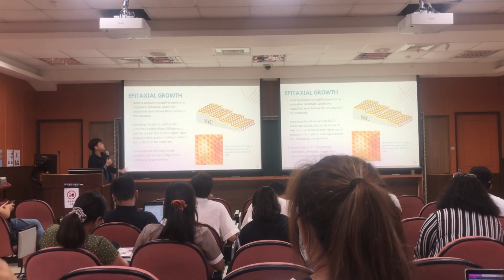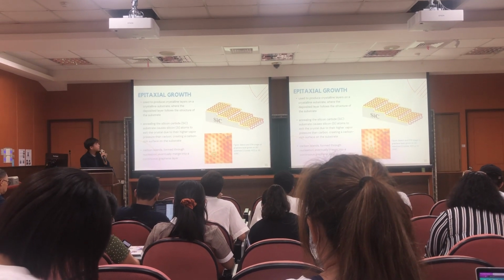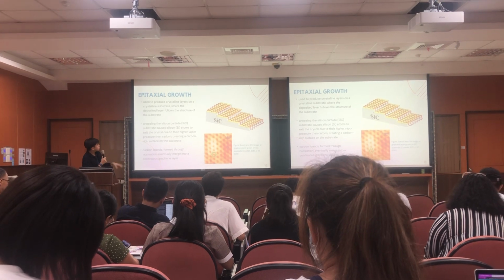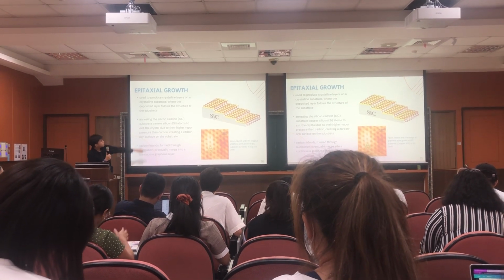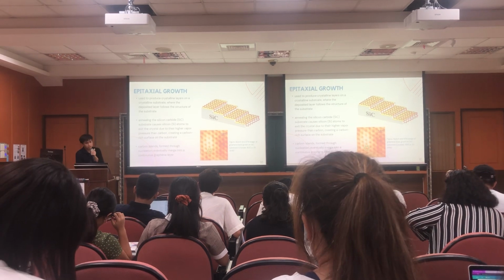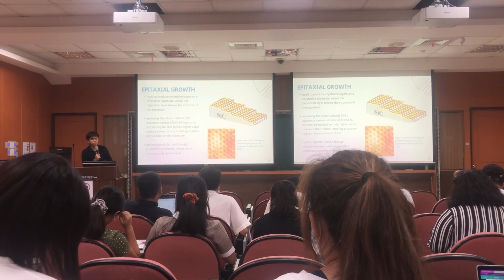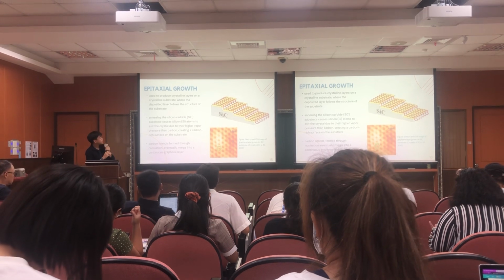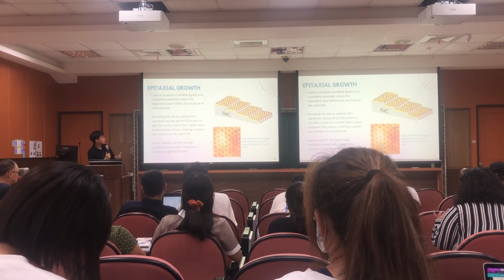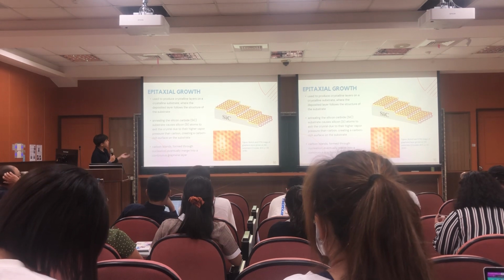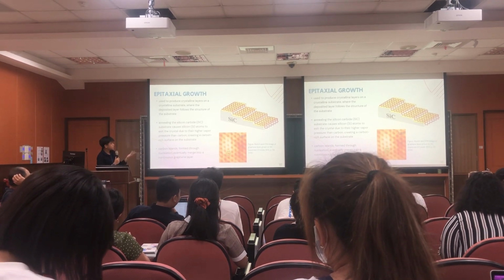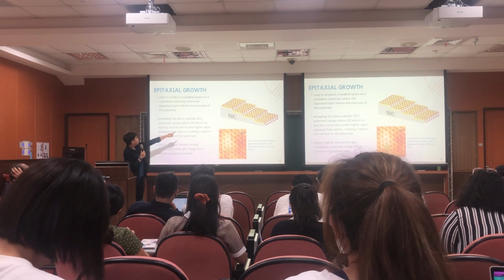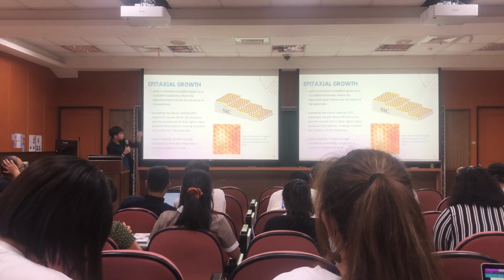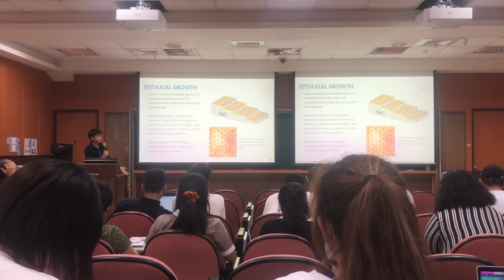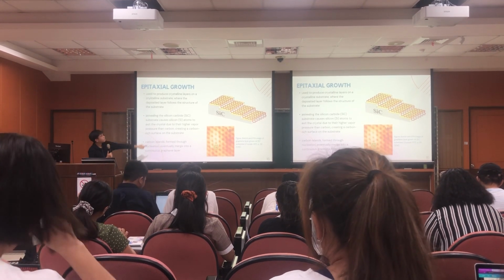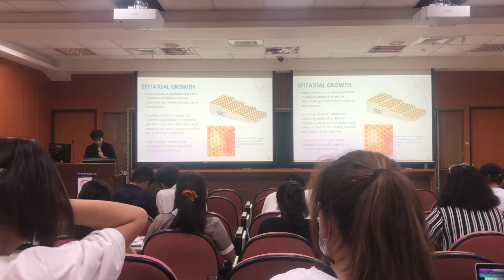The final graphene synthesis method that we will cover for today is epitaxial growth. It is used to produce crystalline layers on a crystalline substrate. So we have silicon carbide in the figure on the right, where the deposited layer follows the structure of the substrate. So it's generally more organized as a graphene synthesis method, in that your output is more organized in its crystalline structure. Annealing your silicon carbide causes the silicon atoms to exit the crystal, which leaves your layer of carbon and graphene as a result. The carbon islands formed through nucleation eventually merge into one continuous graphene layer, as seen in the figure.